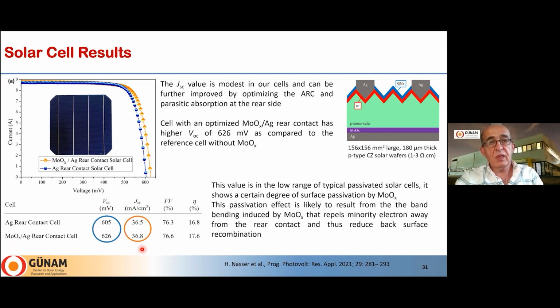Of course, the short circuit current value needs to be improved, and fill factor needs to be. So we believe that this solar cell can be improved to give us an efficiency value close to 20%. This is a standard solar cell, by the way. The front side is a standard one, and there is no heterojunction on the front side.